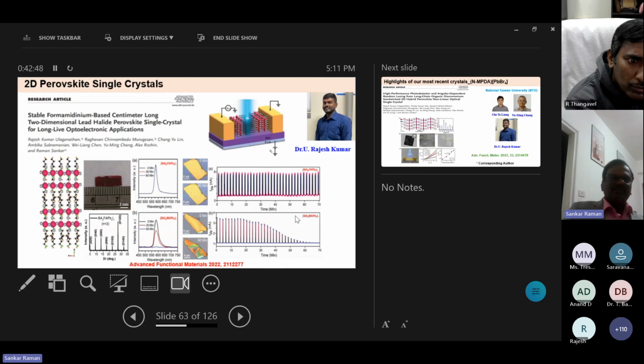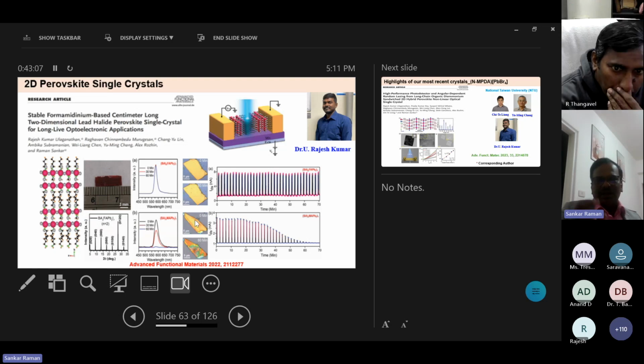Another thing: there is a big problem with methyl ammonium N equal to 2, because most people grow that one. The problem we face is the stability of the material. You can clearly see at the bottom the butylammonium methylammonium lead iodide, in the PL measurement. At 0 minutes the PL signal is stable, then at 30 minutes it is quenched, and after 1 hour it is completely 0.